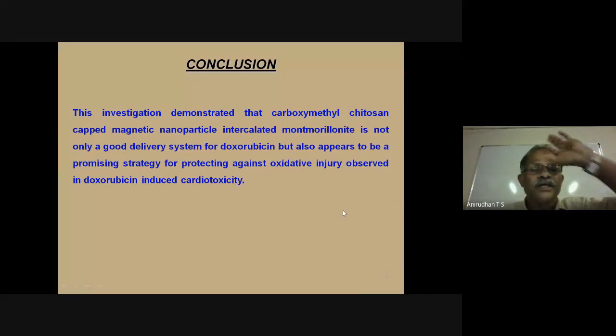What is the importance of this material? I want to conclude like this. This material demonstrated that carboxymethyl chitosan capped magnetic nanoparticle intercalated montmorillonite is not only a good delivery system for doxorubicin, but also appears to be a promising strategy for protecting against oxidative injury, especially doxorubicin induced cardiotoxicity. Actually, when you use this doxorubicin, there is a side effect: cardiotoxicity is there, so we want to introduce this to capture reactive oxygen species and repair this damage, especially in this cardiotoxicity.